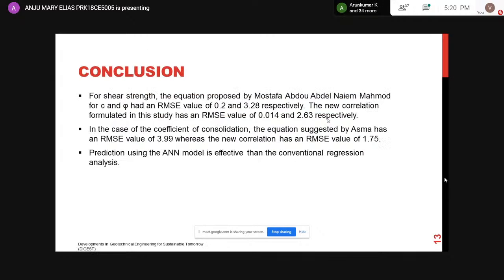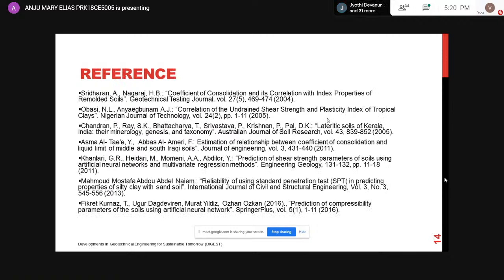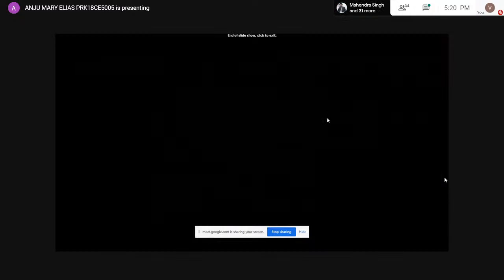So it can be concluded that the equation suggested by Mustafa had RMSE values of 0.2 and 3.28 for cohesion and angle of internal friction respectively, while the equation which we have predicted has comparatively lower RMSE values. Similar is the case of the equation suggested by Asma for coefficient of consolidation. And also ANN is proved to be more efficient than the linear regression analysis, and the predicted equations can be used for Kerala soil. These are the conclusions from this study. These are my references. Thank you.